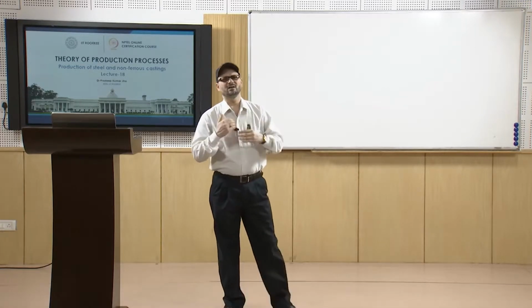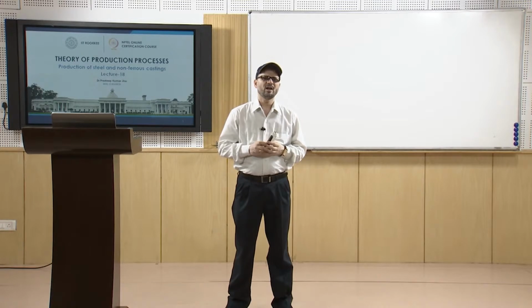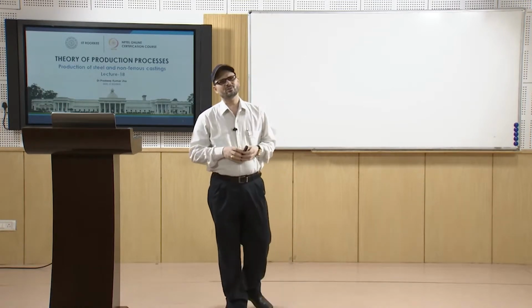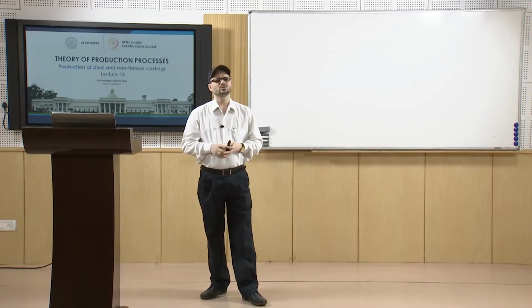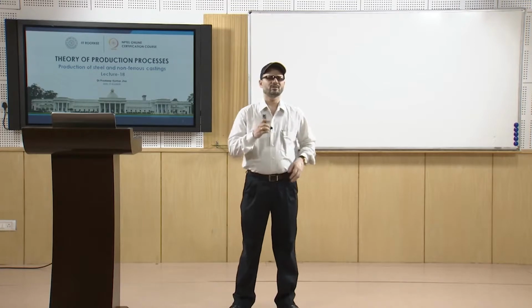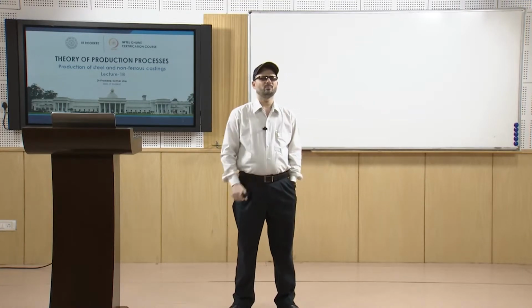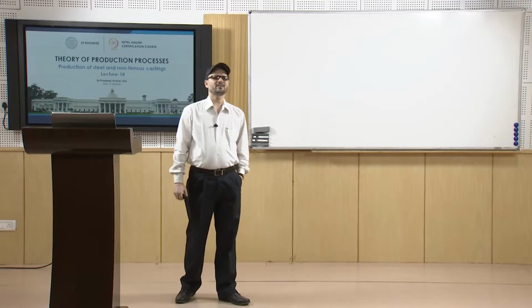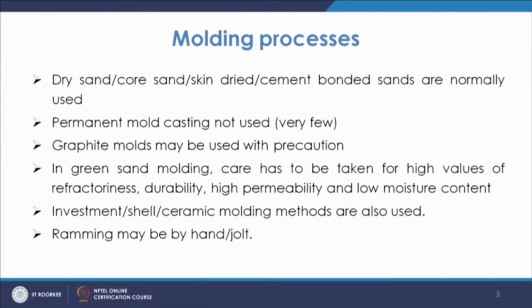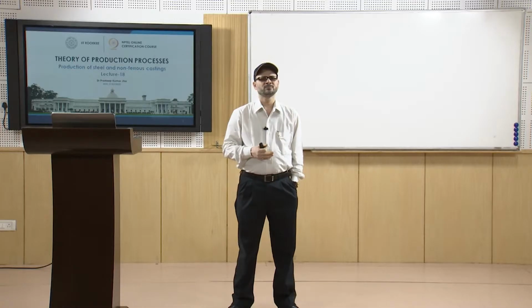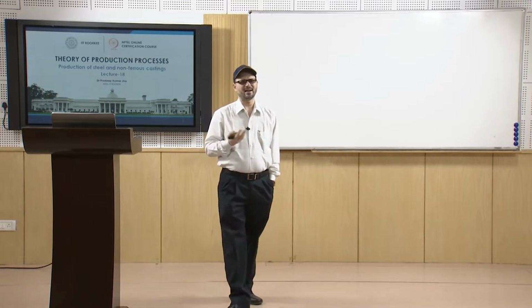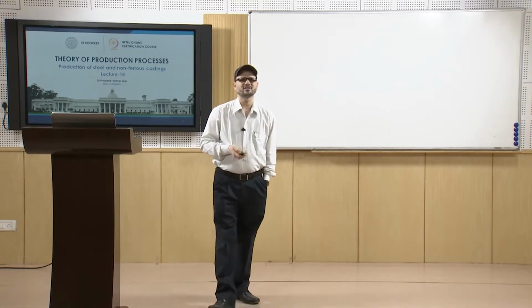So for that the mold has to have extremely high permeability and also low moisture content, because the more the moisture content, the more the gases or vapor formed. So that needs to be driven off. So for that you have to take care of these points like high refractoriness, durability, high permeability and low moisture content. Investment casting, shell molding, then ceramic molding methods are also used, but their use, like investment casting, will be limited by size. Then ceramic molding also may be used for typical applications. Then the ramming has to be done either by hand or jolt machines. So that is normally the practice in case of steel molding.